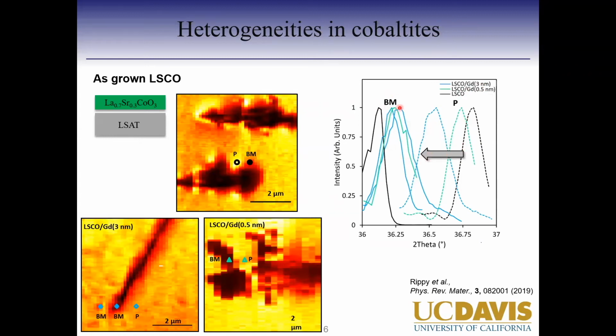And then the brownmillerite itself is not the same lattice parameter for every sample. So the lattice parameter differs widely, and even within one sample, like the blue, it could actually differ. And so using this sort of localized two theta maps, we can actually map out the strain of the entire perovskite phase in the sample.